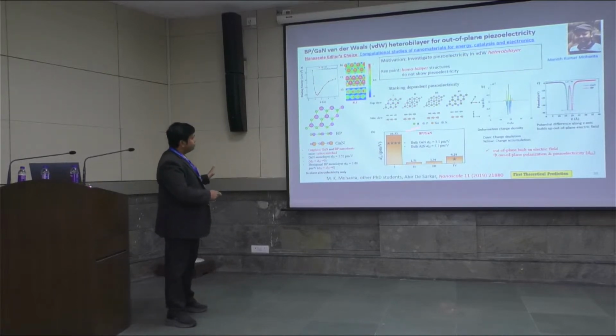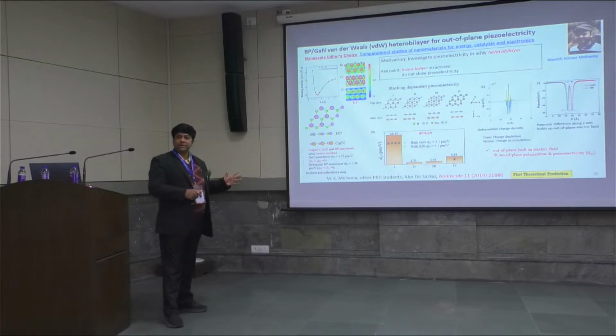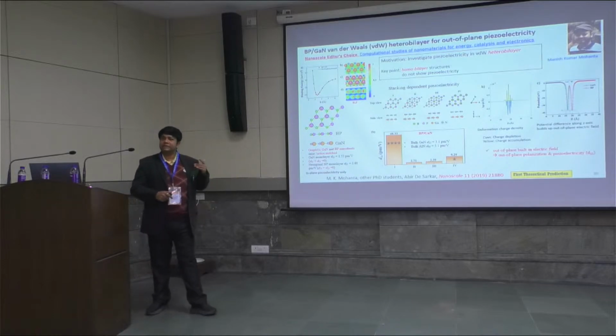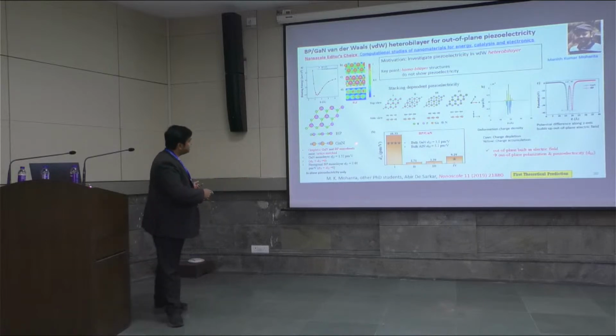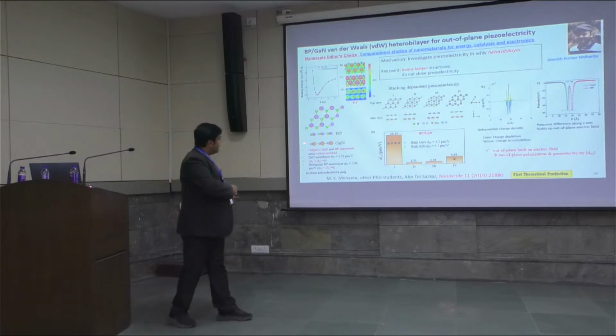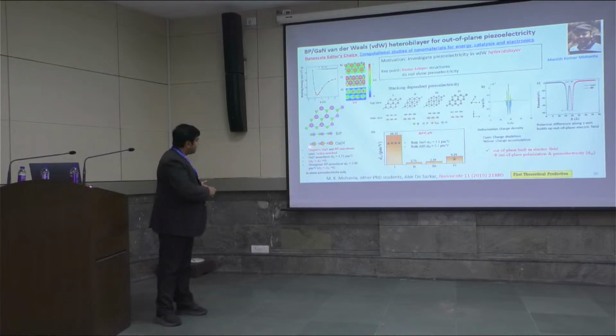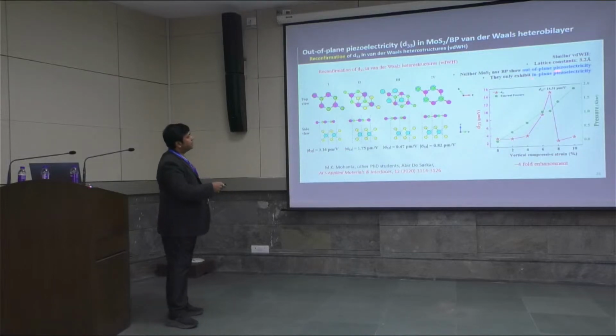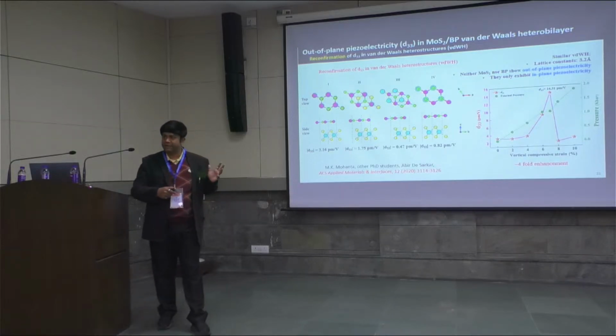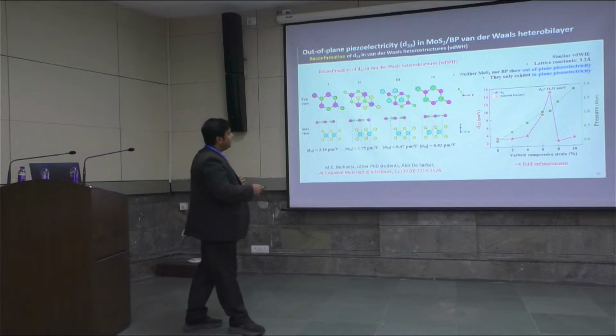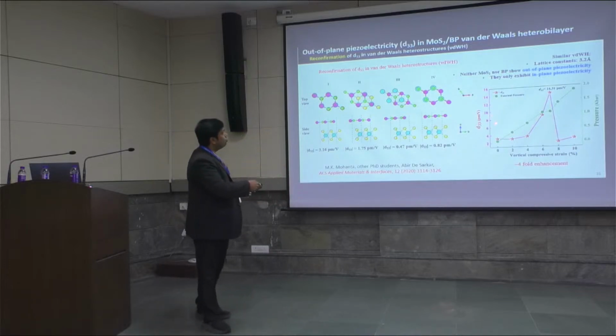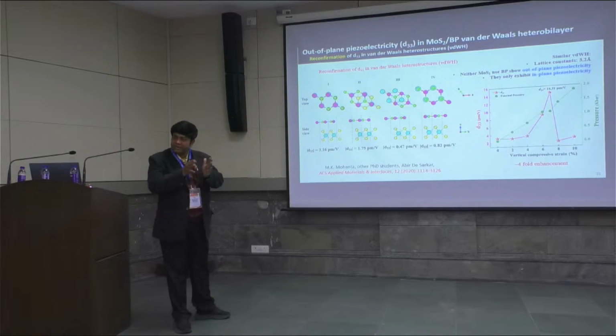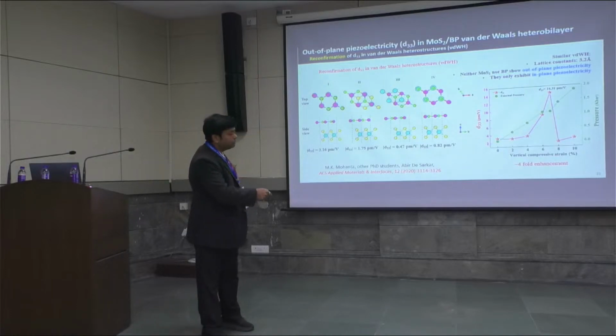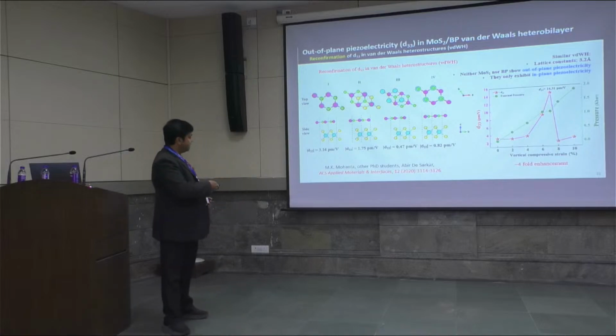Then we tested our understanding on other systems, to see whether the understanding reached here is generally applicable to other van der Waals heterobilayers. So we replaced gallium nitride by a monolayer similar to it, close in lattice constant to boron monophosphide and gallium nitride. We replaced gallium nitride by MoS2, molybdenum disulfide, and we find that our understanding is reinforced in this van der Waals heterobilayer as well. And here we find, again, interface-driven properties. When the two monolayers are subject to a vertical compressive strain, there is a four-fold enhancement in the out-of-plane piezoelectricity.